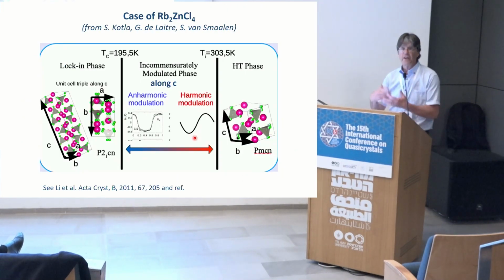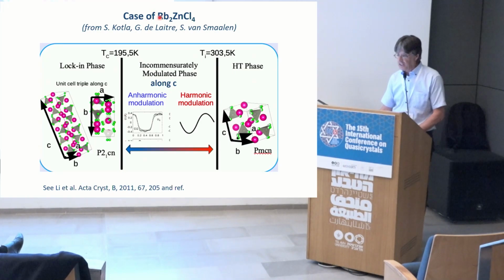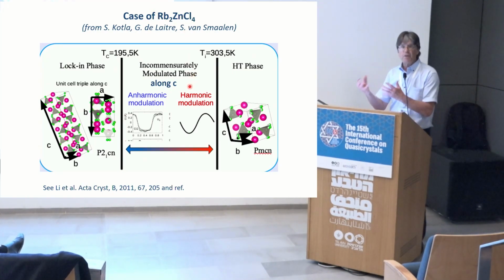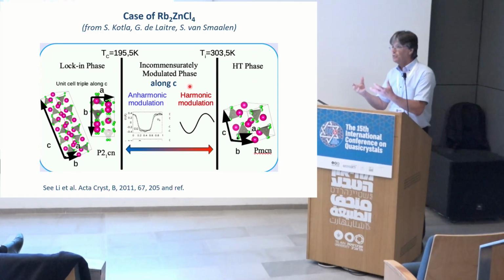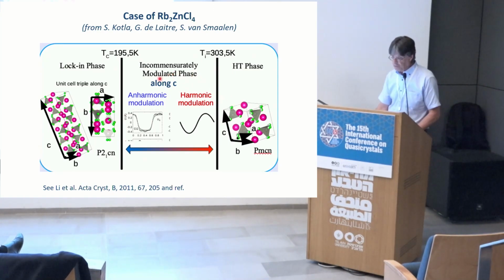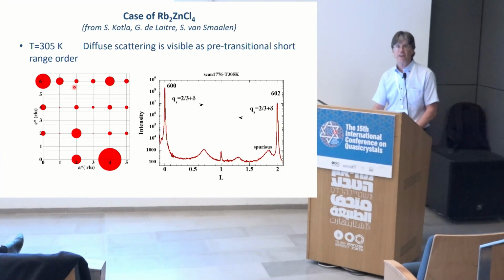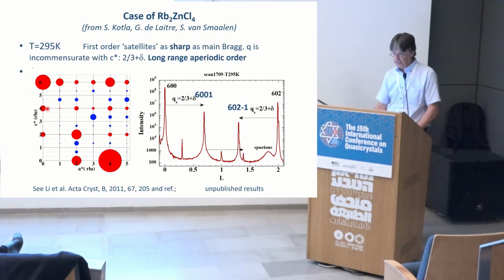If we apply that to a real example, this is the case of rubidium zinc chloride. Tools have been developed using this high-dimensional crystallography to determine the structure. And the structure is disordered at high temperature. It's modulated in this temperature range, just below room temperature, and then it locks in. And how does it look? If you look at the diffraction pattern, that's the high-temperature phase. Here you have only two bright peaks, and this is only diffuse scattering. And if you go below the phase transition, you have extra peaks showing up, these blue dots, shown here and here, which are the satellites.